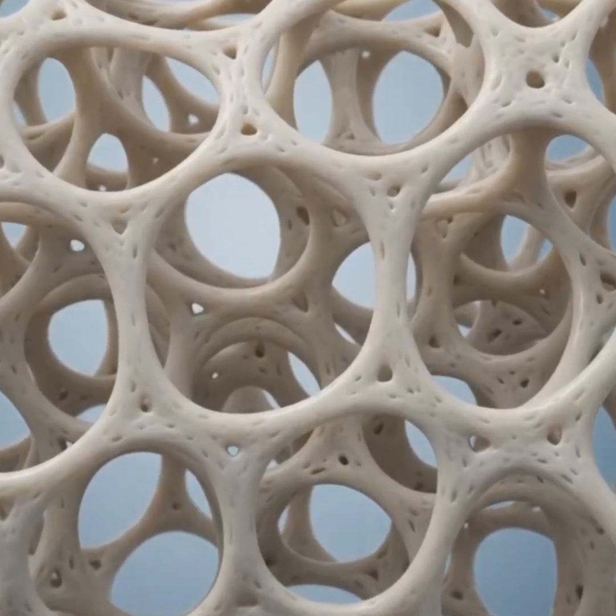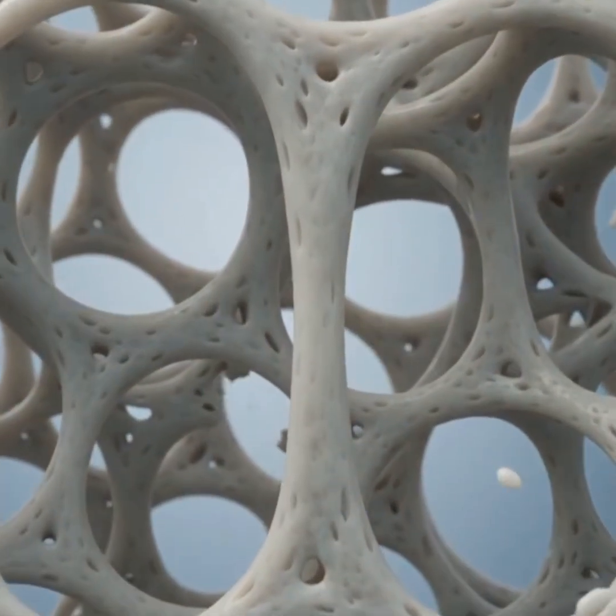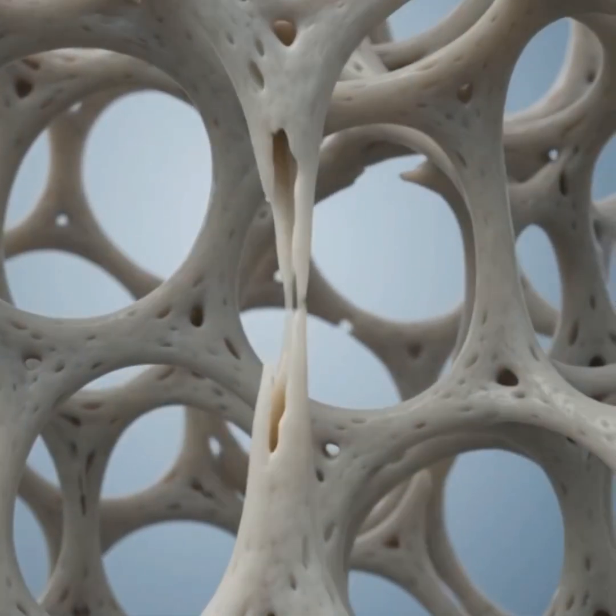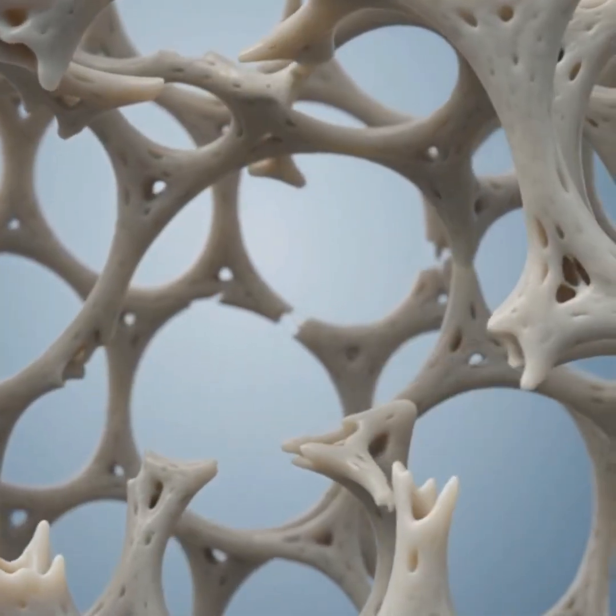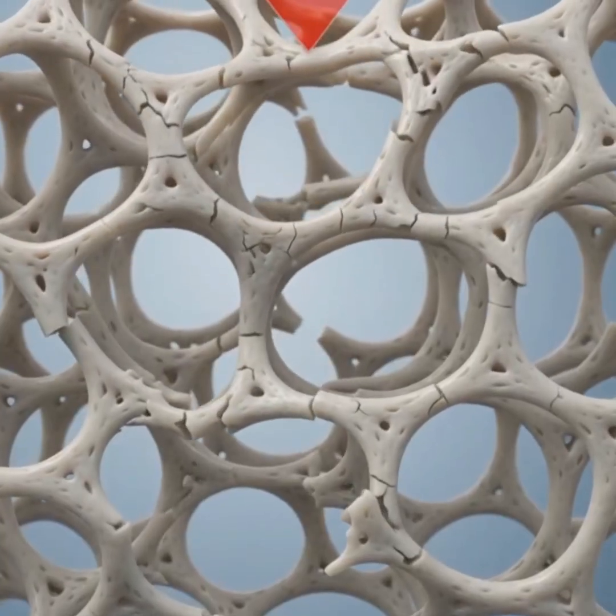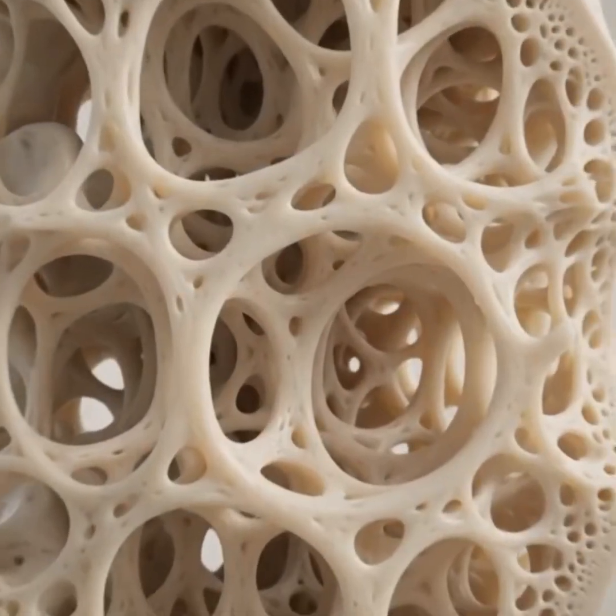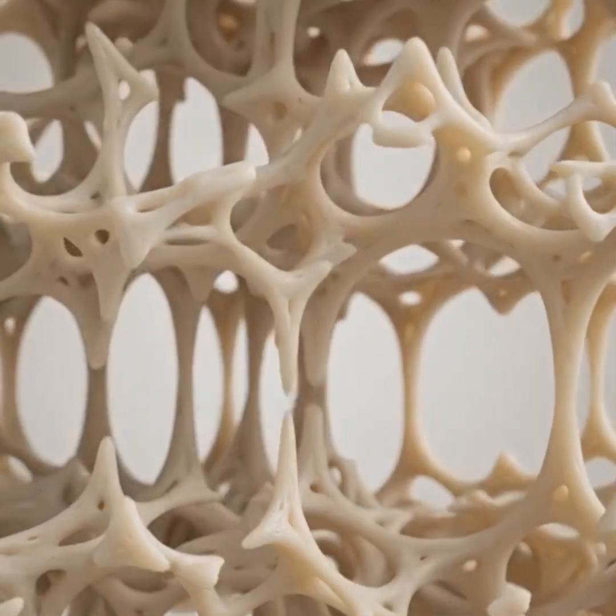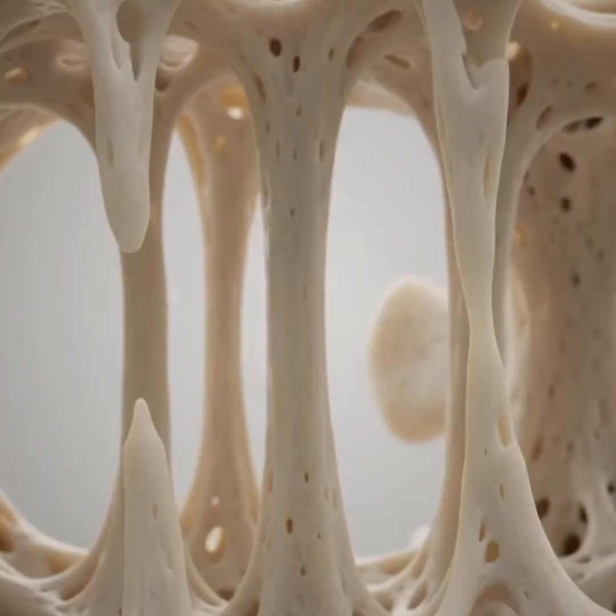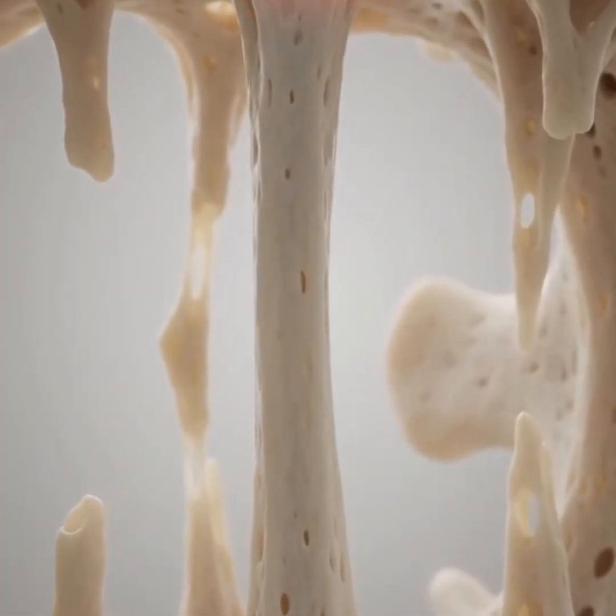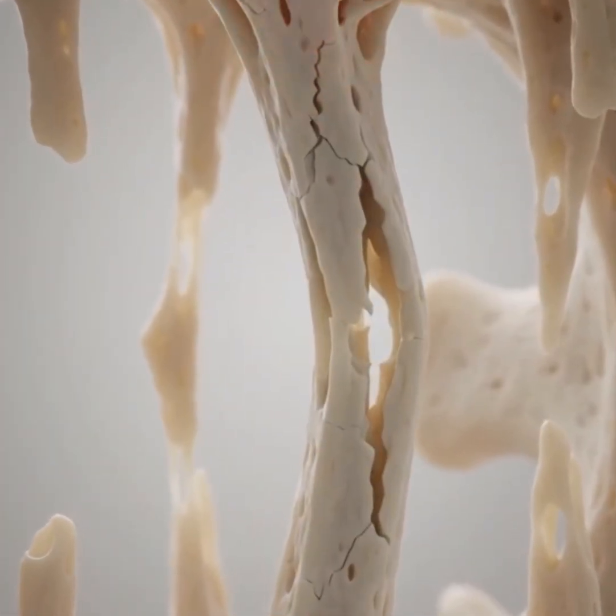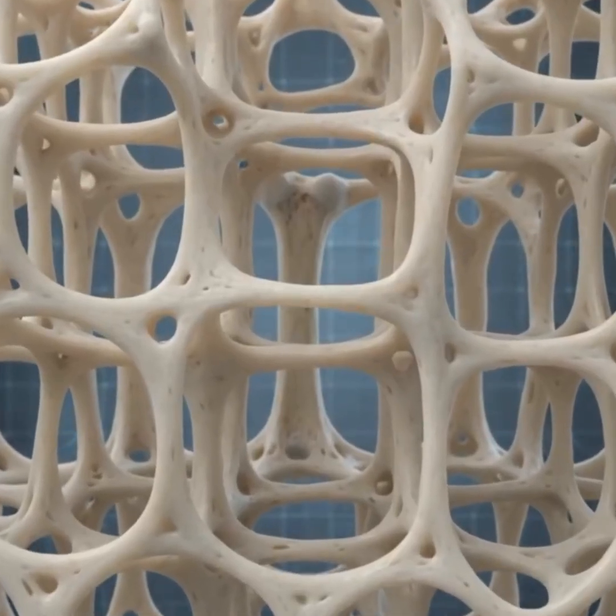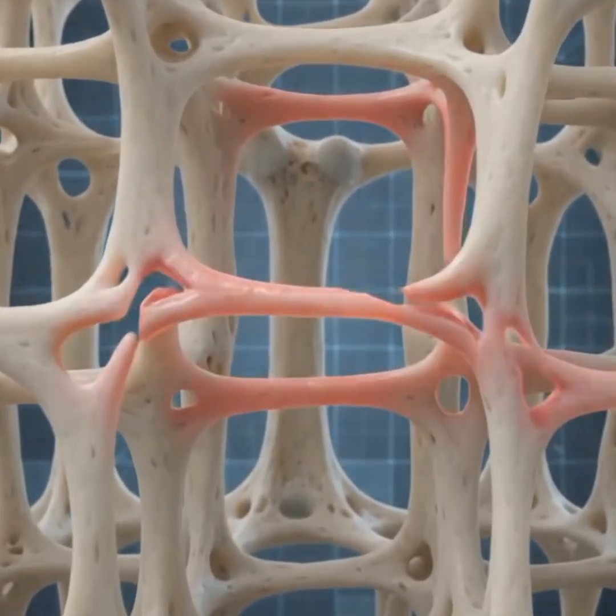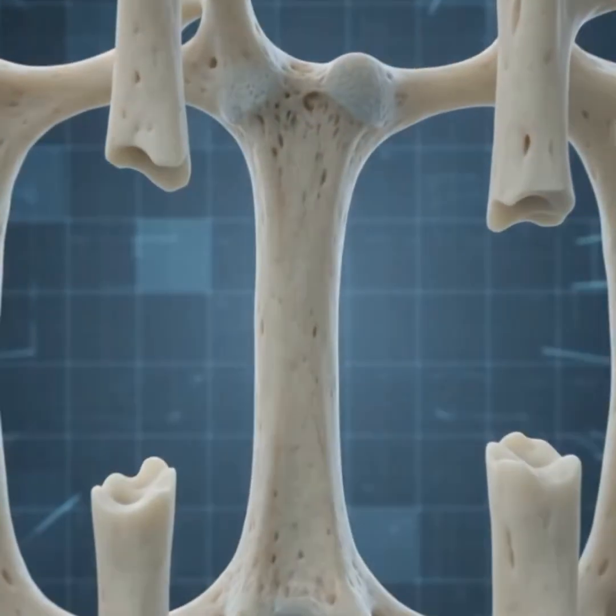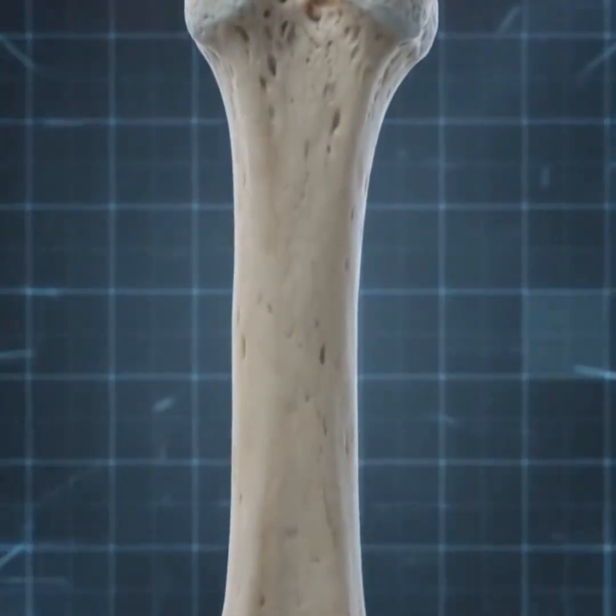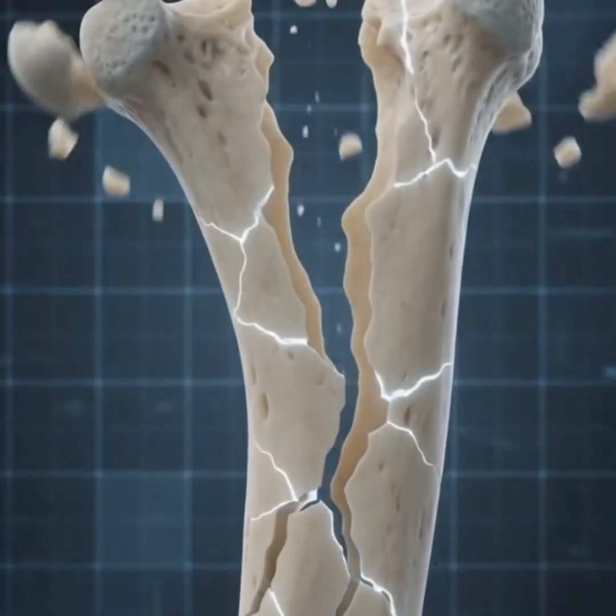In osteoporosis, the trabecular number decreases significantly. This indicates the complete physical elimination and deletion of individual trabeculae. In osteoporosis, trabecular separation is significantly increased. This increases the effective buckling length of remaining vertical columns. In osteoporosis, horizontal connectivity is preferentially lost. This removes critical transverse bracing elements, predisposing vertical columns to Euler buckling.